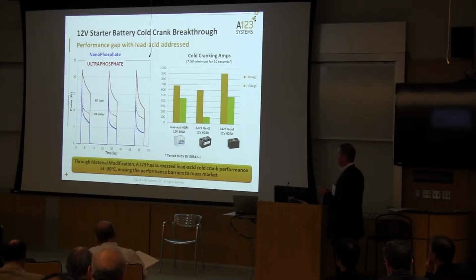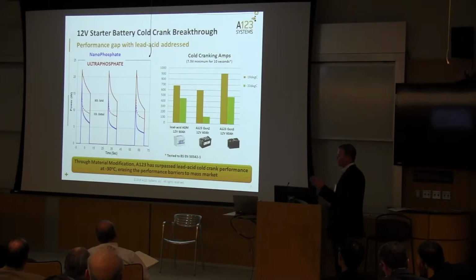So we did pretty well for a while. Essentially, our Gen 2 12-volt lithium-ion starter battery had decent volumes. And we were really supplying to the higher end European automakers, just to support some electronics. The problem is that when you look at our initial LFP, which was actually our Generation 3, and this is our Gen 4 LFP, which was trademarked as nanophosphate.